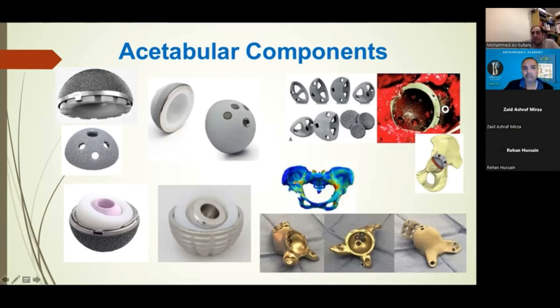I've also put here, for more complex cases, these triflange custom-made implants. Some patients, particularly in revision replacements, not so much in primary replacements, you sometimes face a problem of significant bone loss where you don't really have a socket. On top of that, the type of bone around it may be very weak, and this is like a heat map. But with a CT scan, you can identify areas of bone that are of good quality and bone that is not good quality, where you won't achieve anchorage.